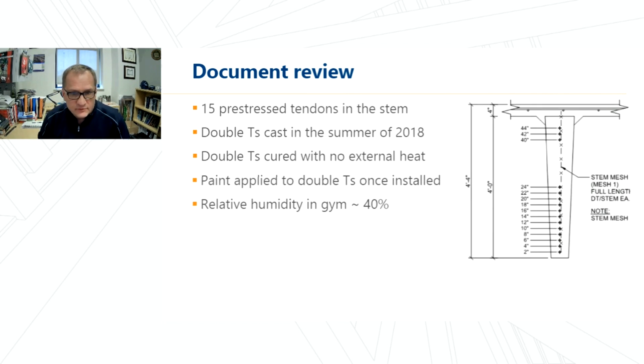We also took a look at the drawings, right? And we found that these double T's have 15 pre-stressed tendons in the stem. And the double T's were all cast in the summer of 2018 in a climate that was quite warm. We also learned that the double T's were not externally heated, meaning no external heat like steam was applied during the curing process. We often see issues related to DEF in precast elements when external heat, like steam, is applied to the product. They did not do that in this particular case.